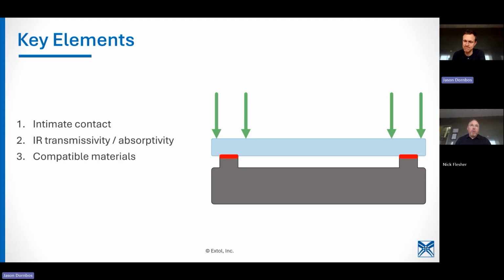Yeah. We do find that we get a lot of glass-filled nylons because this is a really clean process, arguably the cleanest process for welding plastic. And so we do get up to 30% glass. Now, what's really key on that is consistency. So we can get through a lot of glass. It's an insulator, but it actually does transmit light. So we can use some glass, but when we see maybe a gate where the glass doesn't flow through consistently, that can be a challenge. Longer fibers can be a challenge for consistency. So really good answers, everyone. Appreciate that.